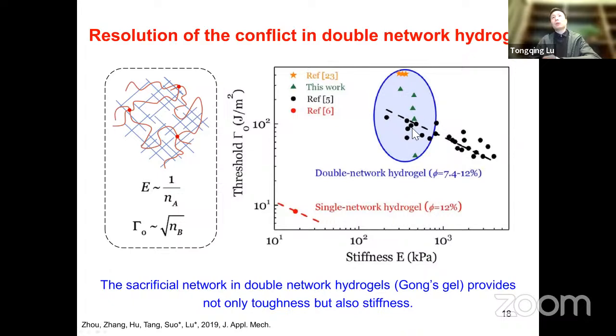And to verify this, we also prepared many different kinds of hydrogel. We only change the chain length of the long network, but keep the short network at the same concentration. We can see the green data and the star. So the stiffness almost does not change, but the threshold can be improved about 1 order of magnitude. So we can see the double network hydrogel design actually resolves this stiffness and threshold conflict.